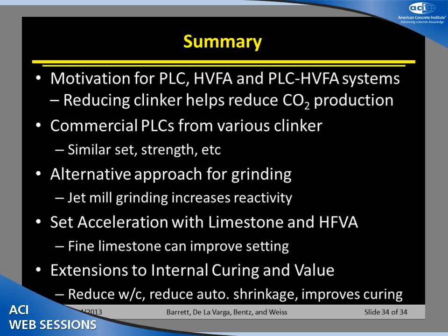I will say anecdotally, we've tested in the lab where if you have rapid drying, you see a reduction in plastic shrinkage cracking with internal curing. As far as how this affects bleeding, there's not a substantial impact on bleeding that we've seen. One of the things we have noticed, though, is these materials are less sensitive to plastic shrinkage cracking because you have that additional water inside of the system.